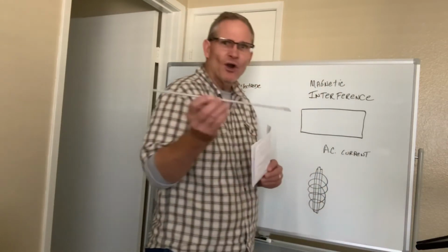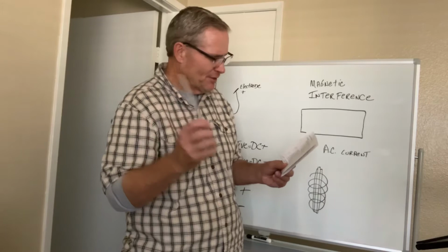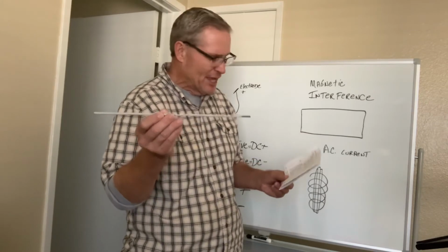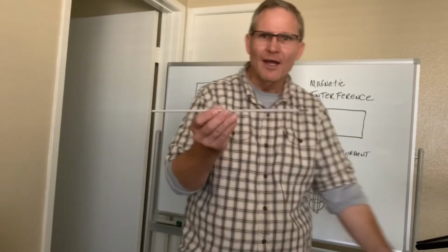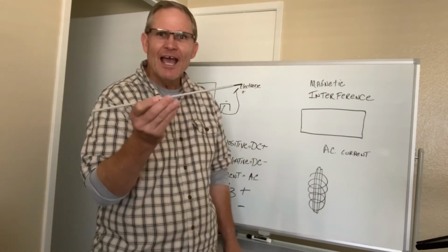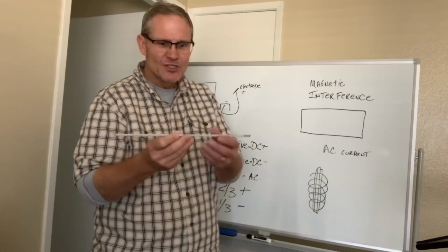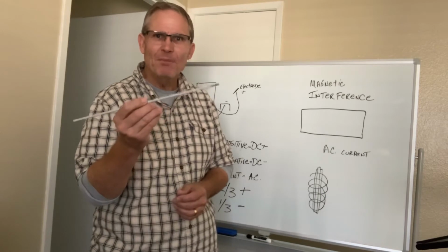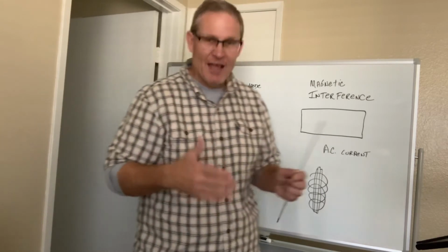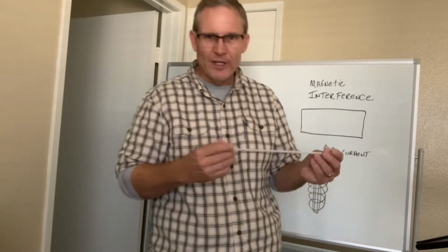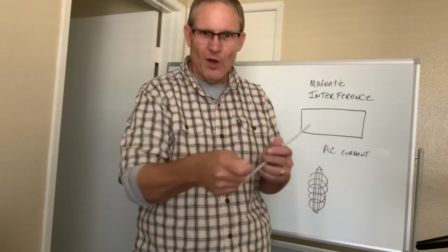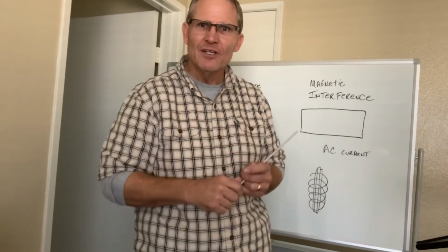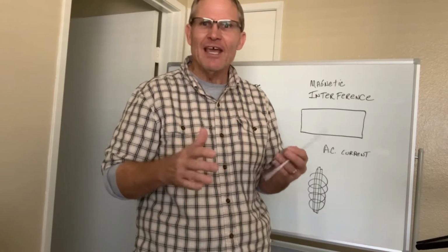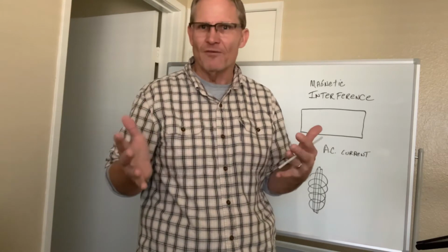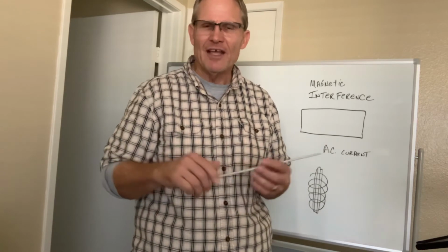This common electrode that I was talking to you about earlier at the beginning of this lecture is a 7018 electrode. And this electrode can only be run on alternating current and DC plus. So you cannot run this electrode on DC minus. And I've found that in the industry, where someone is welding 7018 and I go back to the welding machine and they're hooked up to the negative terminal, that means that their work is non-certified. It needs to be removed. And that's exactly what we did.